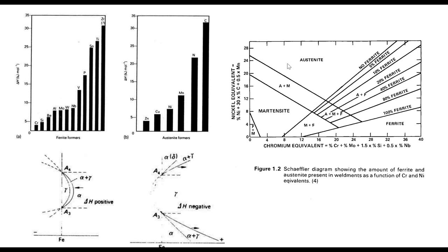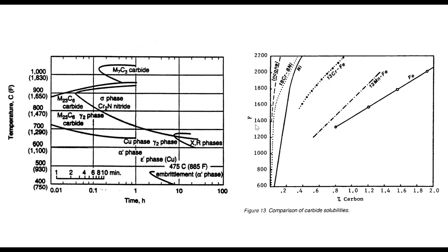If I want the nice soft structure in austenite and I want to go to higher chromium contents, 18% chrome and 8% nickel, because I add a little carbon and other manganese to get it up here, I get in this valley and that's where 304 and 316 stainless steel are. So that's why those compositions are there. If I add more chromium and less nickel, I can make a 50-50 ferrite and austenite and that's what a duplex stainless steel is. And these are the alloys that affect that.